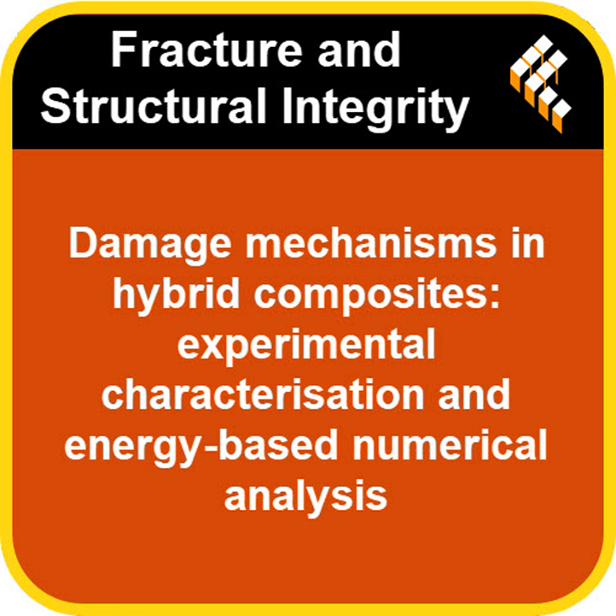And what did the models tell them about when and how that delamination, the peeling between layers, happened? Did it start early or late? Delamination pretty consistently started happening only after the composite had reached its maximum bending force in all the samples they tested. So it's more of a consequence of the main failure starting. That's how it appears, yeah. Pure carbon laminates showed more layer separation compared to the hybrid mixes, while the pure glass laminates hardly showed any delamination at all, which lines up with the idea that carbon fiber fracture might initiate it.